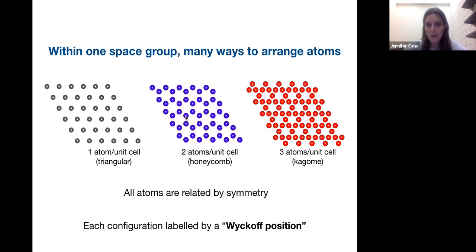But if we now look at the honeycomb lattice, then something different happens. Each atom is invariant under, say, a three-fold rotation. But if you do a six-fold rotation, you'll exchange the A and B sublattices. So on the honeycomb lattice, there's some operations that mix A to B. And similarly, on the Kagome lattice, each atom is invariant under a two-fold rotation. But if you do a six-fold rotation, you'll mix A, B, C sublattices. So each one of these configurations can be labeled by the subgroup of symmetries that leaves one atom invariant. And that's what's called a Wyckoff position. The Wyckoff position is just a way of labeling these different types of configurations.